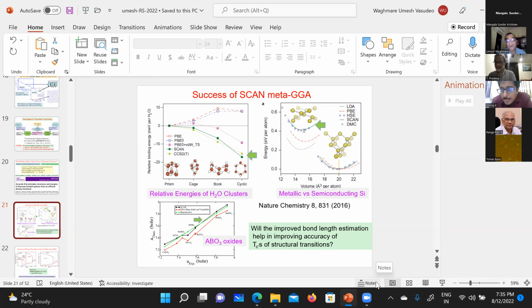Yeah. See, if you already have a model Hamiltonian, which is obtained after coarse graining, then there is not much one can change at the oxidation state level. But you could include effects of those changes in a simplified model form in the model Hamiltonian. Coming back to your question, you must be familiar with even lithium cobalt oxide, which you often study with lithium vacancies, and there are changes in the oxidation state of cobalt. In principle you have to change even the Hubbard U parameter which is used for cobalt. And there is no simple way in which you can predict what the right U parameters should be. So this is an open issue.